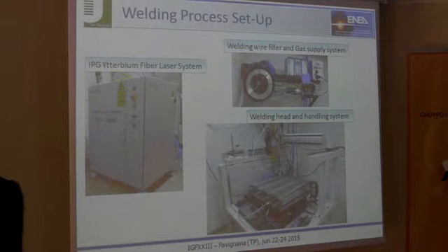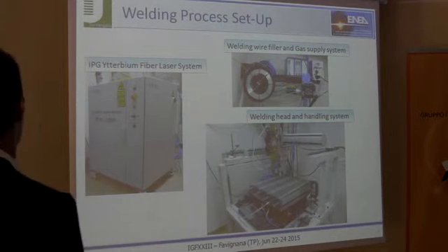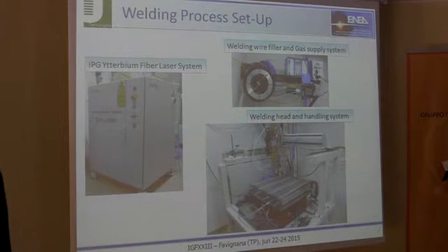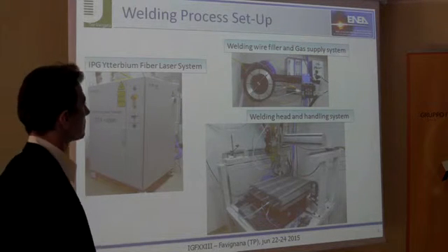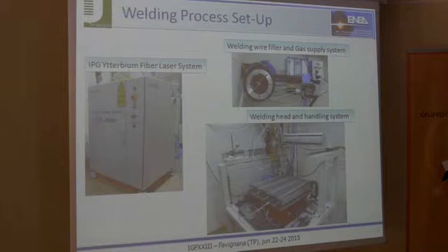Now, the welding process. Why did we choose the laser welding process? Aluminium welding is affected by the issue of softening, in particular at the level of the heat affected zone. And laser allows realizing very narrow pits with low heat input, and thus minimizes the heat affected zone. The power source that we use is an IPG fiber laser system with an output power of about 2.3 kilowatts.